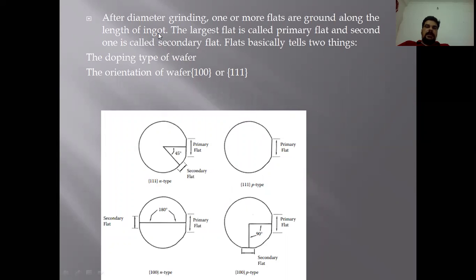Now after diameter grinding, there are certain flats that are assigned to the wafers. The major flat, the largest flat, is called the primary flat, and the second one is called the secondary flat. So these flats basically tell two things. One is the doping type of the wafer, and another one is the orientation of the wafer, whether it is a 100 or a 111 condition.